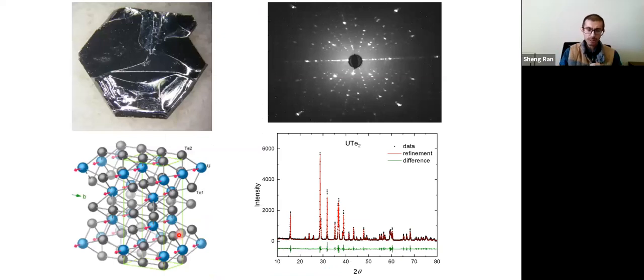Turns out, the first few times when I tried to make this compound, I kept getting a different compound. From X-ray, you can see this is uranium ditelluride. So instead of uranium-7 tellurium-12, I keep getting uranium ditelluride. But you really get very nice single crystals. And from the Laue pattern, you can see a very nice Laue pattern. So clearly you want to do something on this.